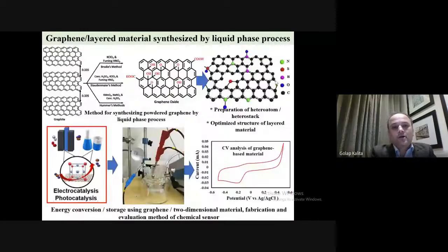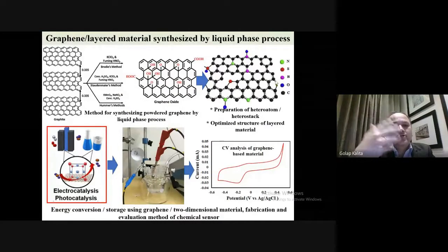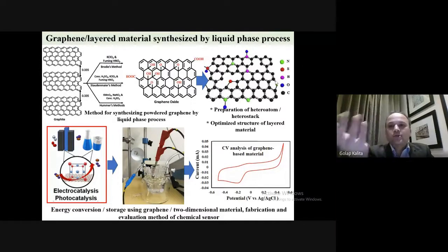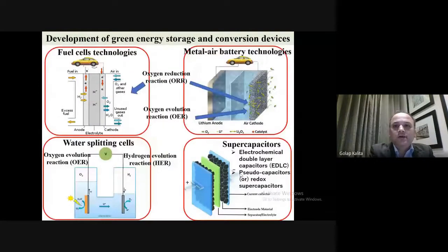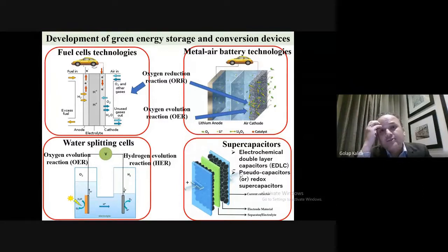First of all, in this case we start with graphene. When you oxidize graphite, you can make graphene oxide, and you can dope it with various heteroatoms like nitrogen, sulfur, or boron, and you can make them catalytically active. We measured various electrochemical analyses in this type of cell, and this is a CV analysis of some materials. What is coming here is fuel cell technology, where the oxygen reduction reaction is very important.